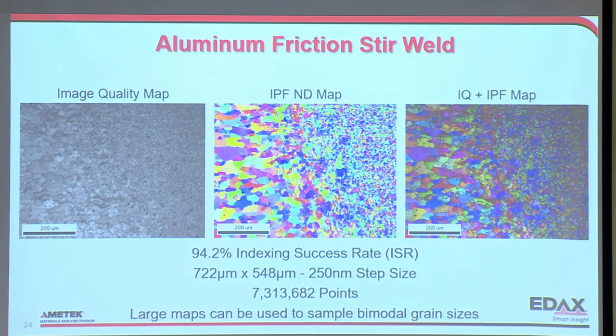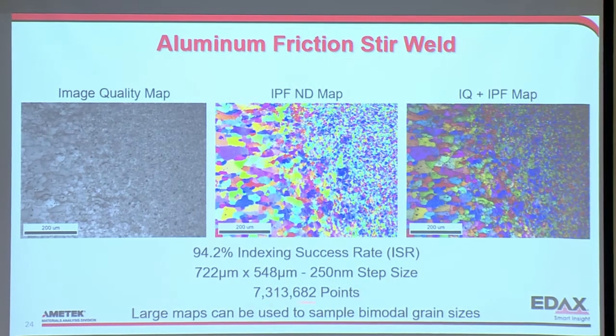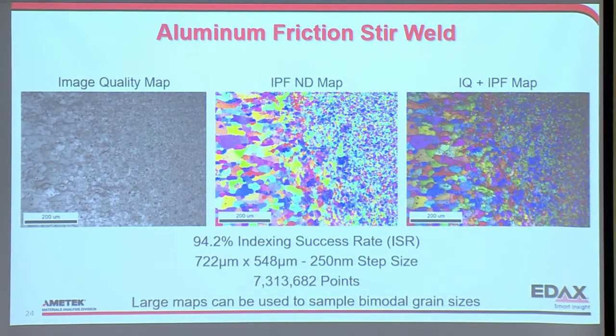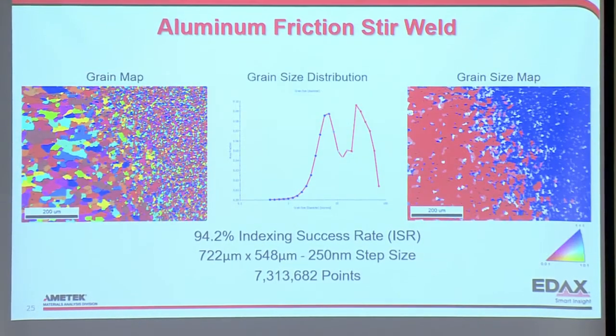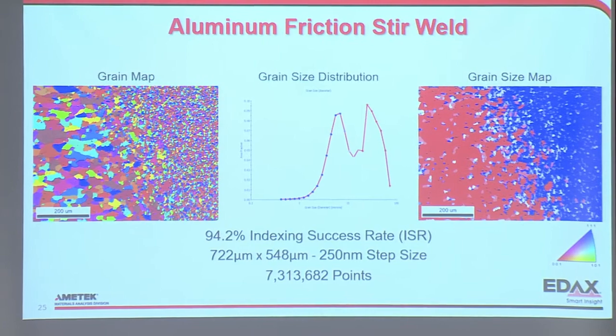This is an aluminum friction stir weld. This is a nice example because we have these large grains here, small grains here, and 7 million points to capture this bimodal grain size. And it comes out well.